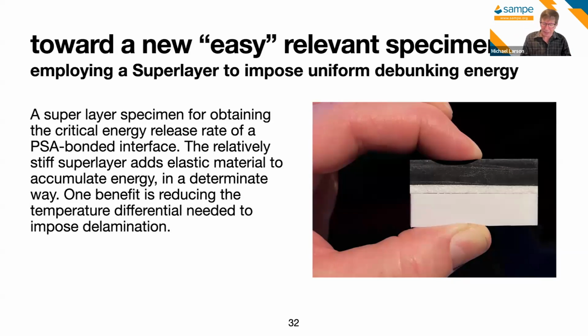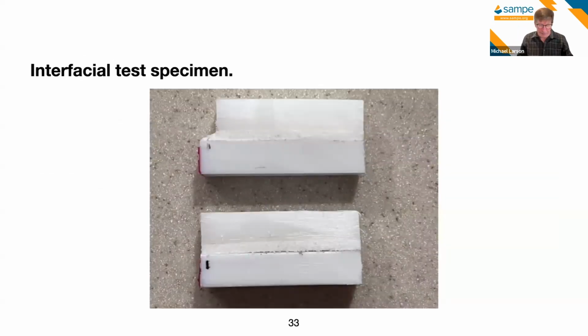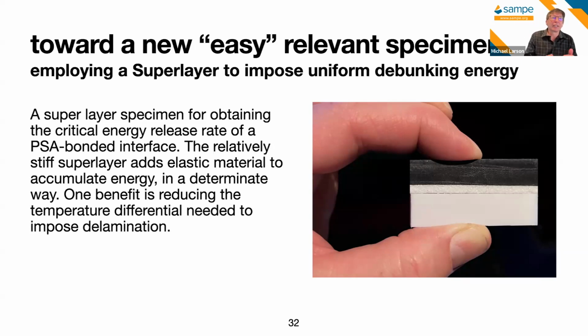and this was something suggested to us by John Hutchinson at Harvard I mentioned before, because this is a technique often used in the area of thin film metal coatings in order to try to get at the delamination levels for those types of structures. There's no reason we can't apply it to the notion of getting a known and uniform stress distribution to drive the delamination, so we can have a specimen that allows us to unambiguously try to pinpoint a useful value for using in the analysis, much like our analogy to a stress intensity factor exceeding the fracture toughness. Here we want to work toward a factor characterizing the interface that we can compare to a known value.